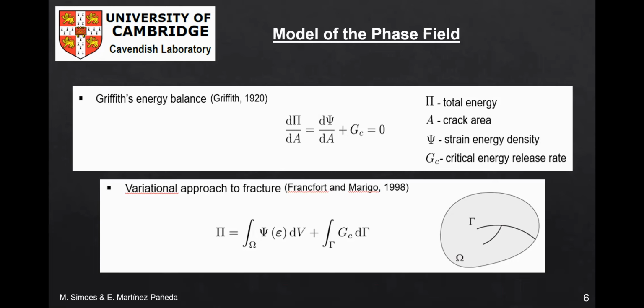This energy balance is the result of considering, in a thermodynamics context, the work required to create two new surfaces. One can formulate Griffith's energy balance in a variational form, with the term accounting for the stored elastic energy in the solid as given by the strain state, and the second term characterizing the fracture energy, the energy dissipated by the formation of a crack.